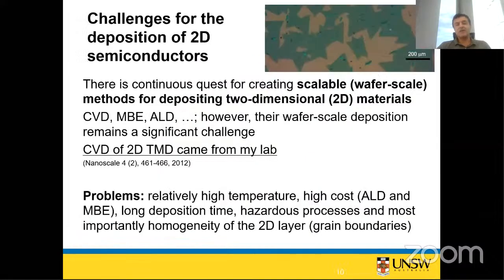So what does it mean? Let's go to the famous two-dimensional materials. We want to synthesize, for instance, a two-dimensional material. For years and years, people have been trying to make these semiconducting two-dimensional materials or graphene using CVD, chemical vapor deposition, molecular beam epitaxy, and ALD. Especially CVD is a very favorable one because you can do it at low cost in comparison to MBE and ALD.